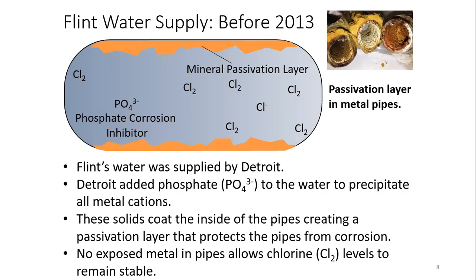Now let's talk about the case study related to the third corrosion strategy, that is corrosion inhibition. This is the case in Flint, Michigan. Before 2013, Flint's water was supplied by the Detroit Water and Sewerage Department. Detroit used orthophosphate as corrosion inhibitor because orthophosphate reacts with lead, forming insoluble lead phosphate that deposits over the inner surface of the pipes, forming a passivation layer. This layer protects the pipes from corrosion because the metal from the pipes is not exposed to oxidation agents in water.